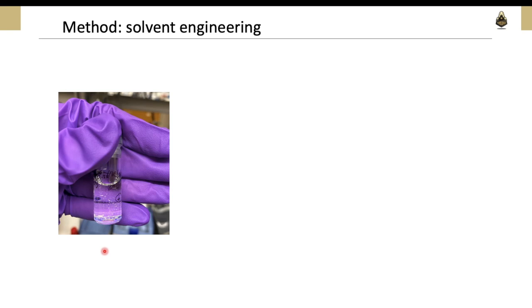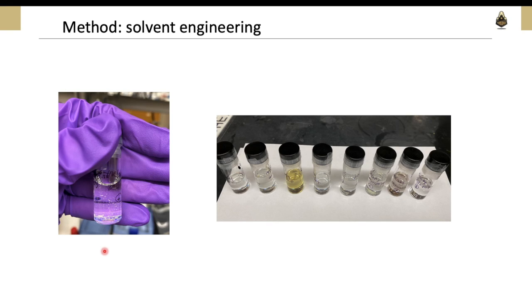To find a common good solvent system for the ligands, we tried isopropanol, ethanol, chloroform, chlorobenzene, and 2-methoxyethanol. Isopropanol and chloroform show low solubility, chlorobenzene shows medium solubility, and ethanol and 2-methoxyethanol show high solubility. However, since ethanol and 2-ME can harm the perovskite layer, we used a mixed solution of 95% chlorobenzene and 5% ethanol as the solvent. These ligands have low solubility in general, so we need to further filter the 2D perovskite precursor solution before we apply it on the three-dimensional perovskite film.